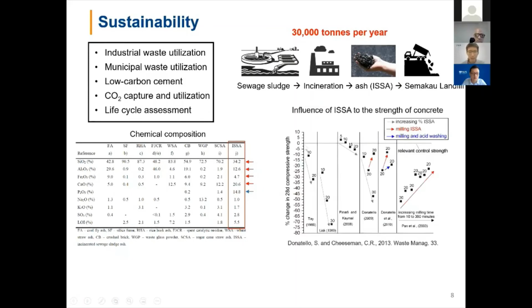There are already some researchers working on this. From the existing studies, we see that some researchers found that adding the sewage sludge ash will significantly decrease the strength of our concrete. But some found that the decrease is very negligible. There's a decrease of only about 10% of the strength if we replace 20% of cement with this ash. And there are researchers showing that simply by grinding this ash, we will significantly increase its reactivity.